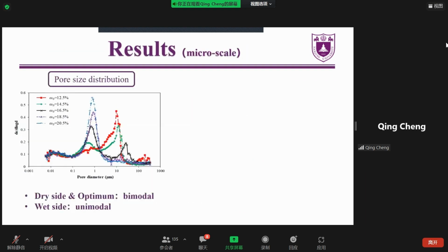And then I will show you some main results of the experiment. The figure on the left-hand side shows the pore size distributions obtained from the MIP test. We can find that for the soil samples compacted on the dry side and at the optimum water content, bimodal pore size distributions with two distinct pore domains can be observed, which means both the micropores and the macropores can be detected by the MIP technique.